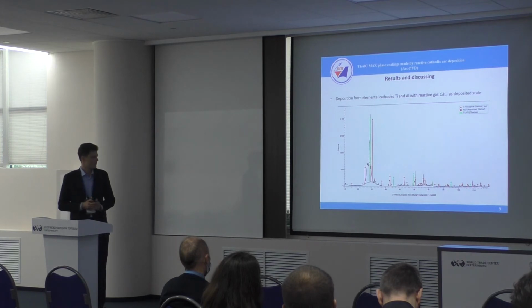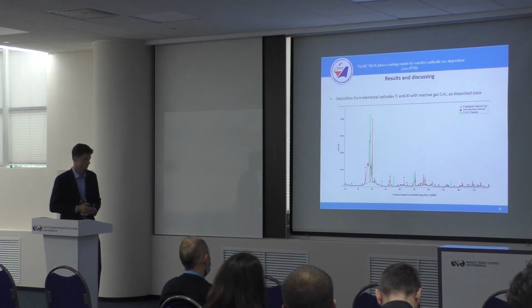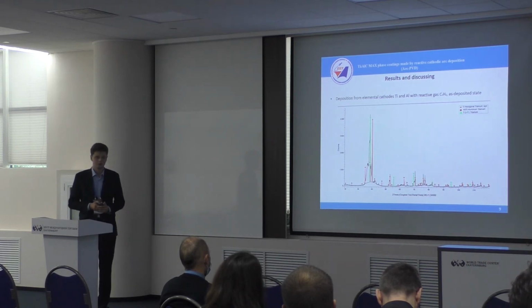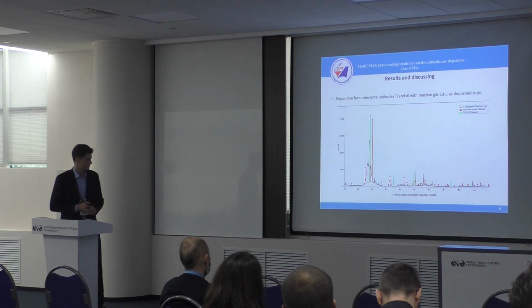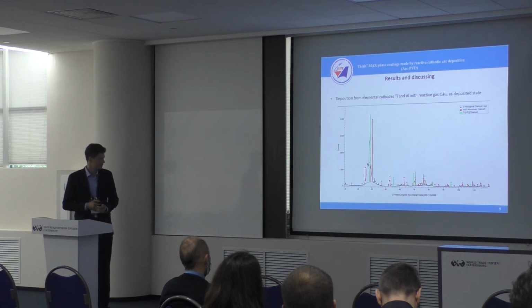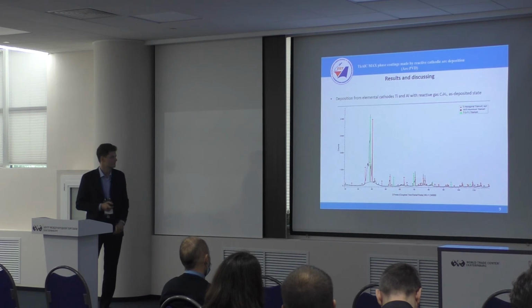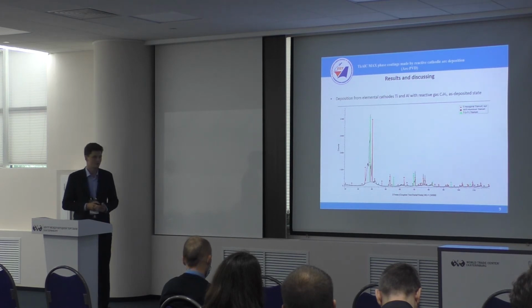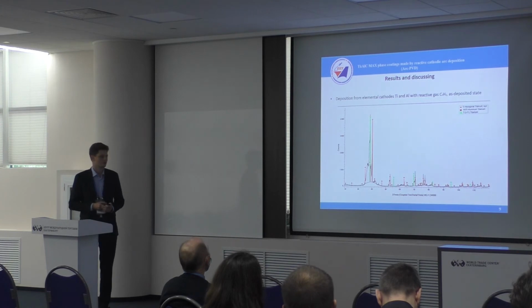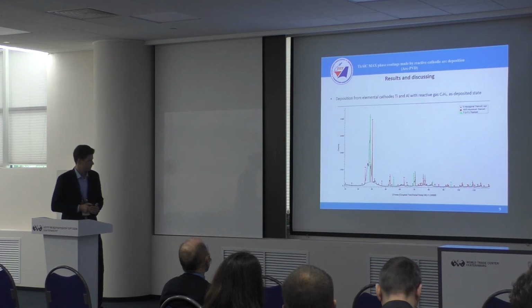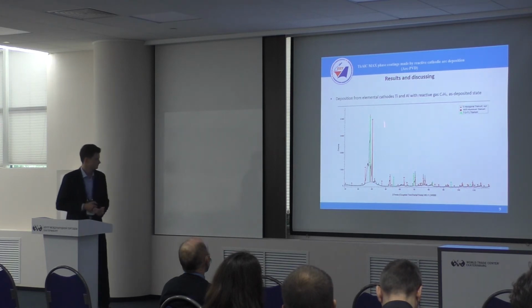This is the X-ray pattern of the sample without annealing. As you can see, there is no signal of MAX phases or even titanium carbides. You can see titanium peaks, alpha titanium peaks and beta titanium peaks. Our substrate was technically pure titanium, and its peak is shown here.